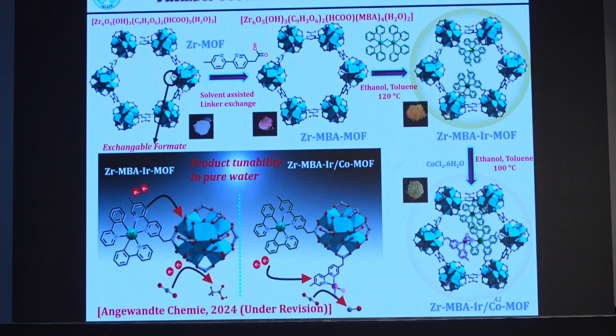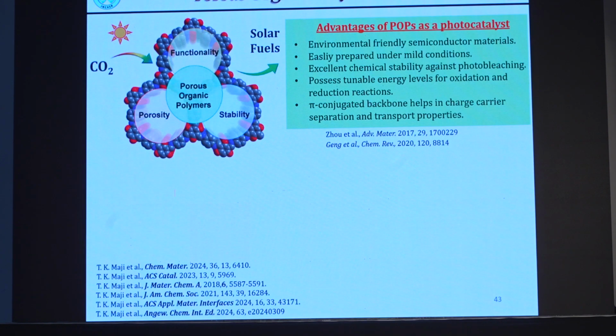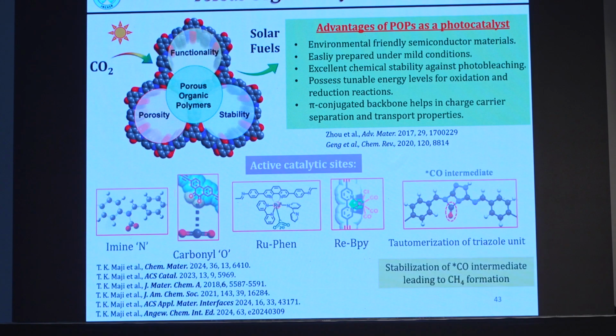Then when the iridium goes to cobalt, we see there is acetic acid. We are getting another 8 electron reduction process, acetic acid. But when you put the cobalt, it can go to the CO. So you can tune the electron transfer pathway here. Okay. So we do a lot of work on other systems, this is not only the MOP, to understand.